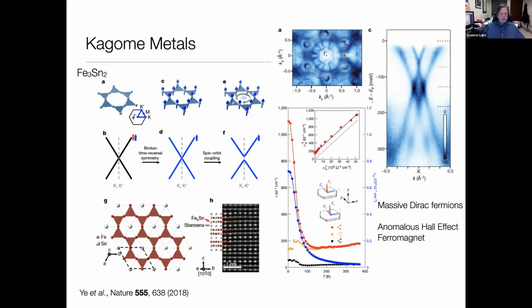So in these materials, in the presence of ferromagnetic ordering, you may have just the spin up part of the band occupied, and then when there's some spin orbit coupling, these two crossing bands repel each other and you get a small gap opening up there. This material was discovered in 2018, so it's quite an interesting topic going forward. First of all, here are some angle-resolved photoemission studies of these materials, and you can see these linearly dispersing bands through here. In fact, you have two bands crossing in the near vicinity of the Fermi level.